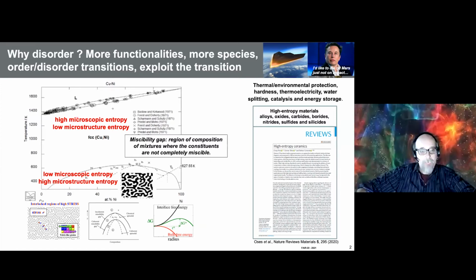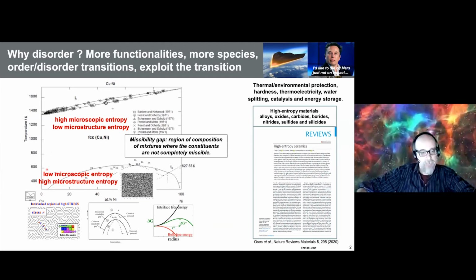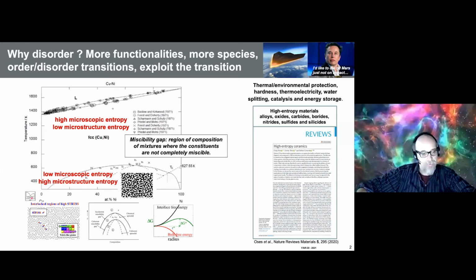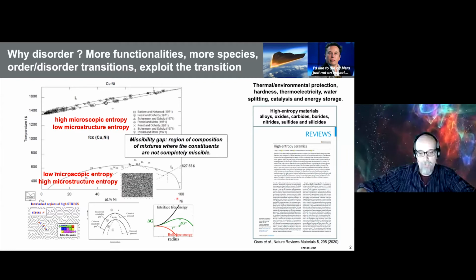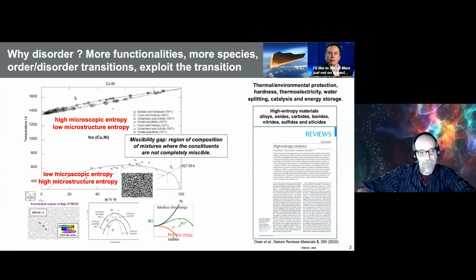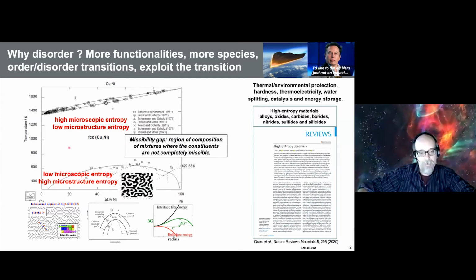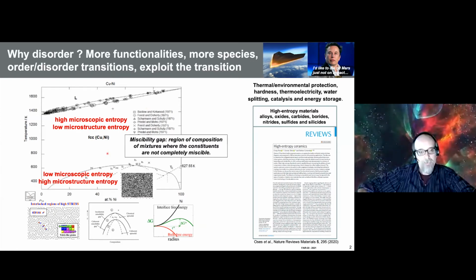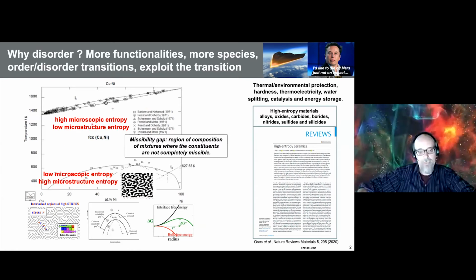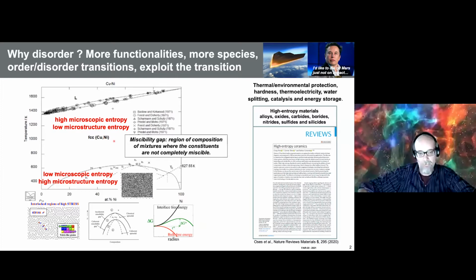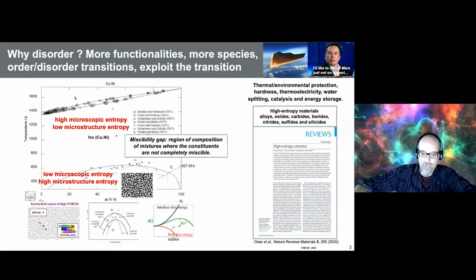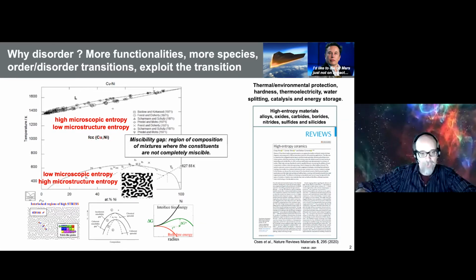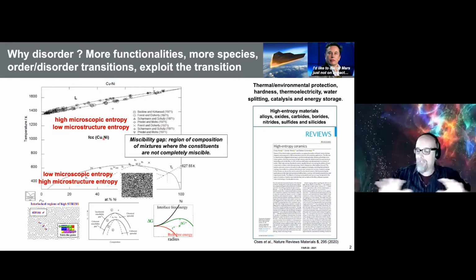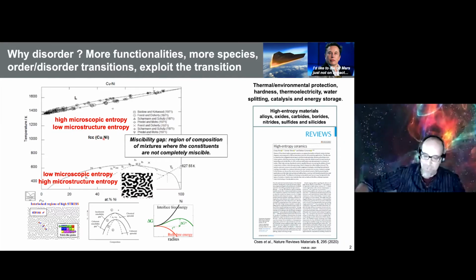Okay, so where is disorder? This is an example of disorder. This is a simple phase diagram, copper-nickel. You see that if you increase the temperature, you have an area in the center where there is a high microscopic entropy and low microstructure entropy. This is the area of what is called solid solution, because both copper and nickel are FCC, so everything becomes a solid solution and substitution alloy.